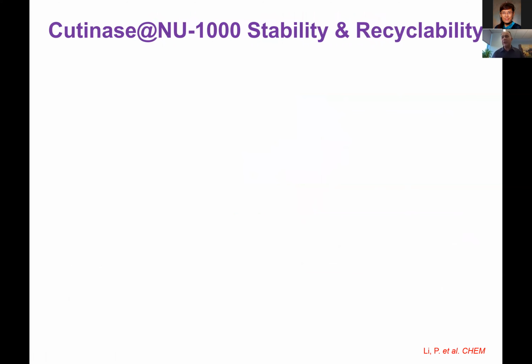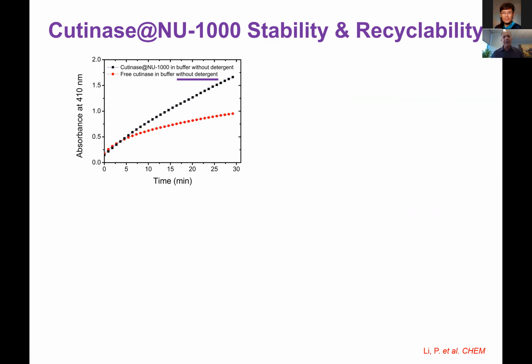So the question is, did we stabilize that enzyme? First of all, this enzyme likes to be around detergent in order to not allow it to aggregate and precipitate. You could say if we don't add detergent to the reaction, our composite is better than the free enzyme. But it's better, but not as better by orders of magnitude. So that's nothing to brag about.